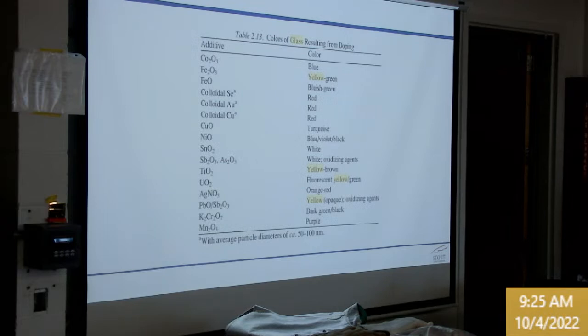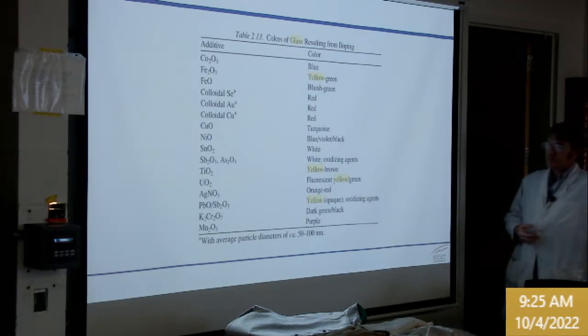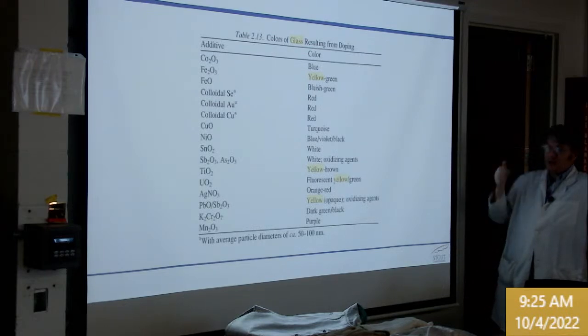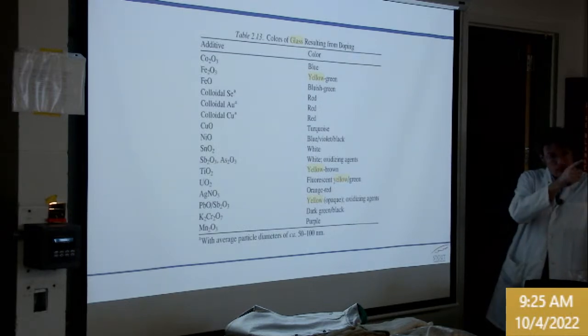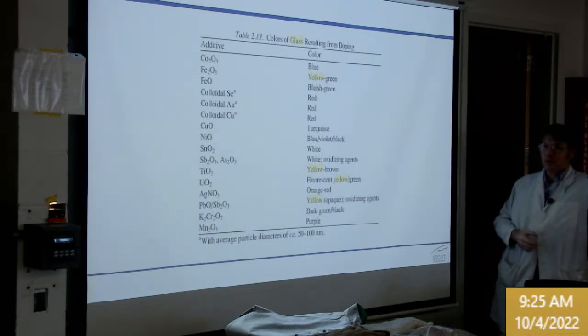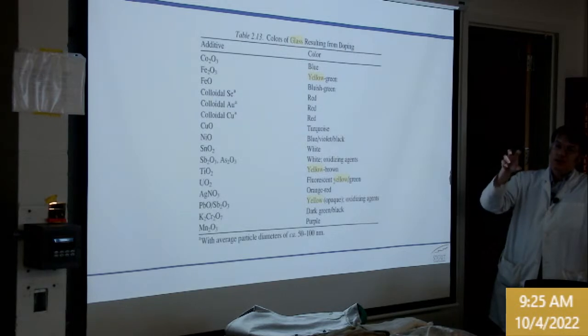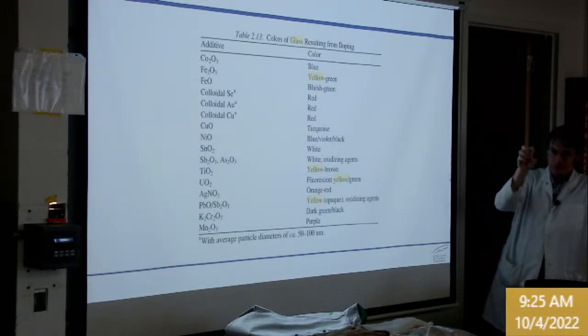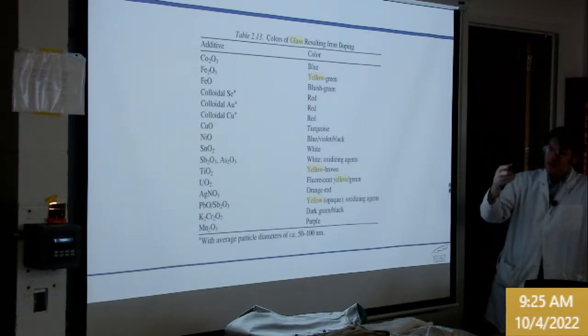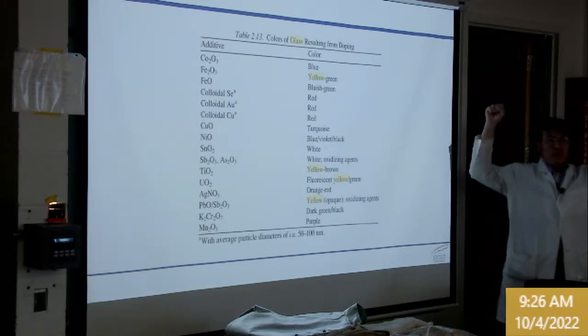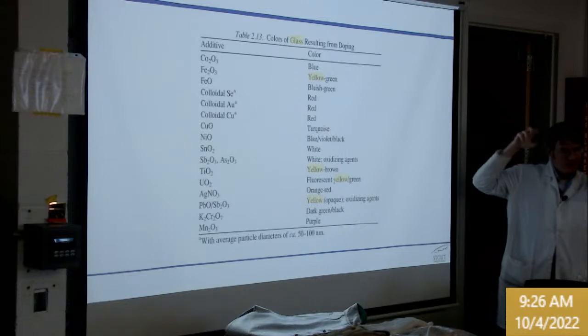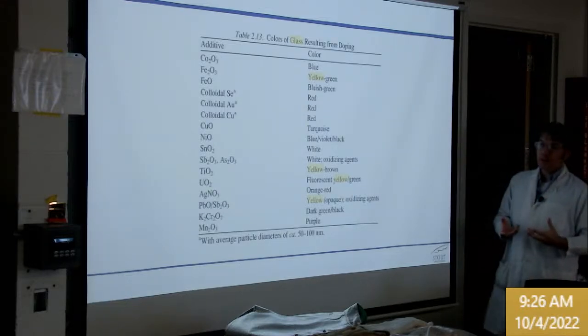When we added our different metal impurities, we obviously changed the optical appearance. Silicon and oxygen and sodium and calcium themselves don't absorb in the visible spectrum. So that makes clear glass much the same as window glass. That's pretty much the batch type that we're making here. But by adding in those metals, it changes how it absorbs light. The way that works is that instead of a silicon sitting in between 4 oxygens, these metals will sit in positions in the glass between 4 or 6 different oxygens and make a coordination center. What's a coordination center? Well, it's a metal that's holding on to 4 or 6 oxygens at the same time. And that has a unique ability to absorb light depending on what metal is there.